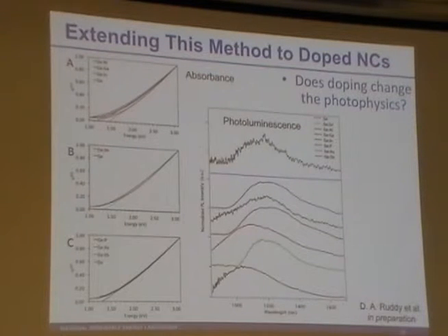Once you get into the 10% doping level, you start to get some formation of the metallic element rather than true doping. The absorbance properties and photoluminescent properties don't change significantly. The only case was the arsenic one, which completely quenched the emission, and we're not exactly sure why. But there are some slight size differences, which is why these things shift around a little bit.